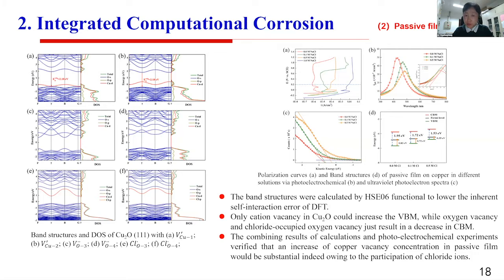Also, we use the band structure with another kind of method, the HSE, so that we can get more accurate results for the band structure. This one shows the combination of the calculation and the photoelectrochemical experimental verification that the increase of the copper vacancy concentration in the passive film would be substantial, owing to the participation of the chloride ions.